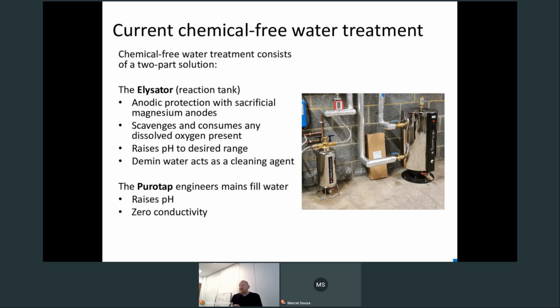Central to that, you have a sacrificial magnesium anode. As water passes through the unit, those sacrificial magnesium anodes sacrifice themselves, so they corrode and scavenge and consume the dissolved oxygen in that system, taking it down to 0.1 milligrams or less. This then releases magnesium hydroxide, which is the chemical reaction from the anodes. This circulates around the system and elevates the pH to the required levels.